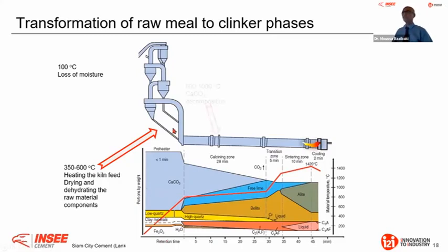Therefore, after that, when the first step is finished, the raw meal goes to what we call the calcination zone. There, the temperature can go up to 1000 degrees C. And this is where the calcium carbonate is transformed into calcium oxide, with the emission of CO2.